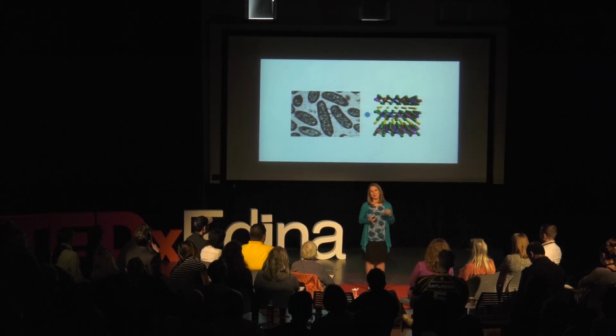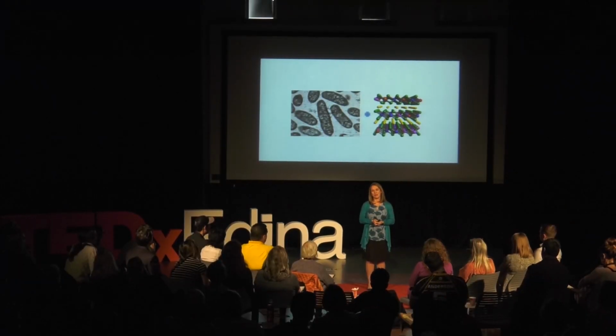But what we did see when we were tracking the bacteria is that in the presence of the nanoscale NMC, they weren't using oxygen like we expected, and they weren't replicating like we expected. Of course, what we wanted to know was why they weren't functioning as we expected them to. If we could understand the molecular reason for the bacterial suffering, we might be able to redesign our particle and mitigate the impact. So, after lots of experiments by hardworking chemistry graduate students, we uncovered the reason that the nanoscale NMC was toxic to the bacteria.